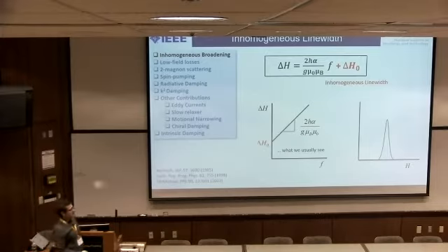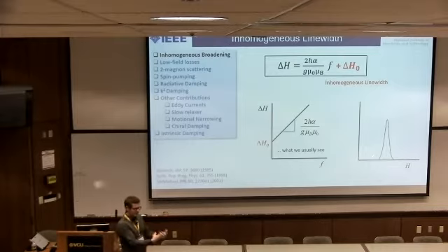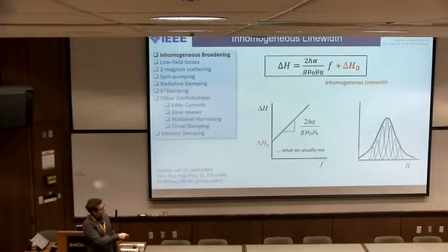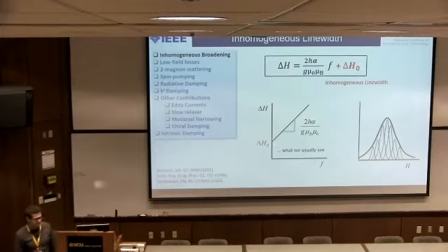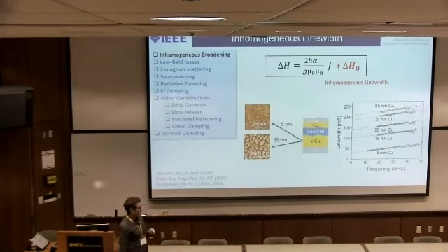From a very basic level, if we have a completely uniform film, we get a nice resonance shown here. But if we introduce a lot of inhomogeneity into our film, of course, we're going to have a whole bunch of local resonances. So in the case of a highly inhomogeneous film, we're measuring basically the envelope of all those local resonances. Now, it's not so simple as a superposition of those local resonances, because we have exchange energy, dipole coupling, and things like that. But that gives you a little picture to start thinking about it.